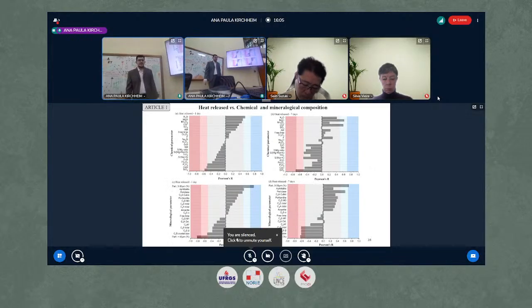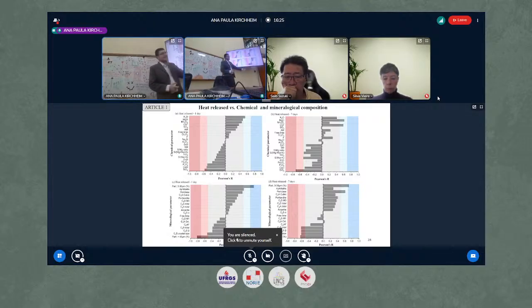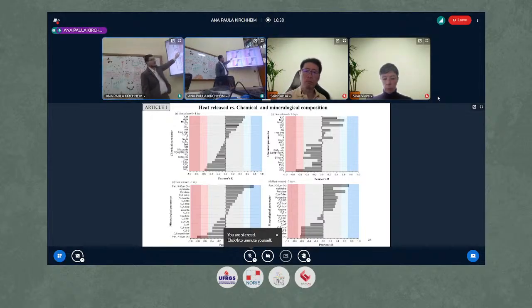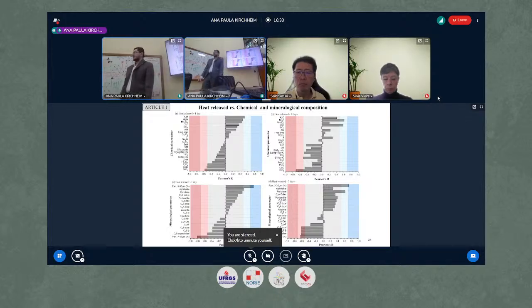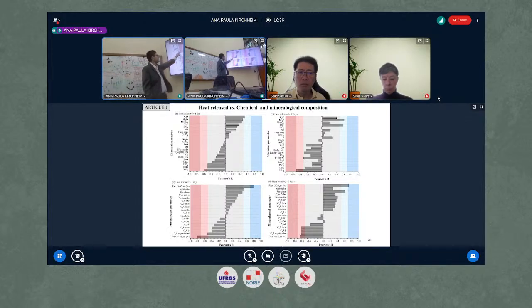In terms of reactivity, here is the main influence on the heat release. We see, as expected, that the main influence was sodium and potassium oxide, the alkalis. The greater the alkali content, the greater the clinker reactivity at 1 and 7 days. And in terms of chemistry, we also see the influence of phosphorus. Phosphorus is a known retarder of cement reaction, but here we see a strong influence at 1 day, but not at 7 days. That is according to the literature as well.